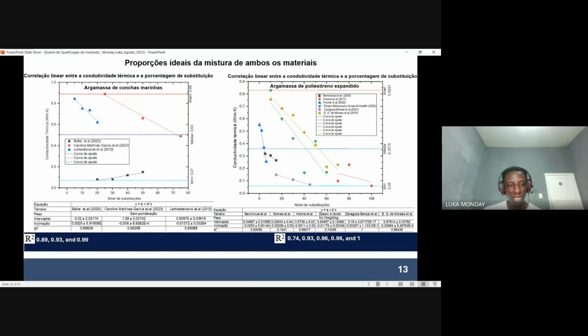So an R square of 0.89 to 0.99 was obtained on the aspect of seashell, while an R square of 0.74 to 1 was obtained on the aspect of EPS, which clearly shows that yes, the substitution level of this material plays a key part with respect to attaining the desired thermal conductivity of each of these materials.